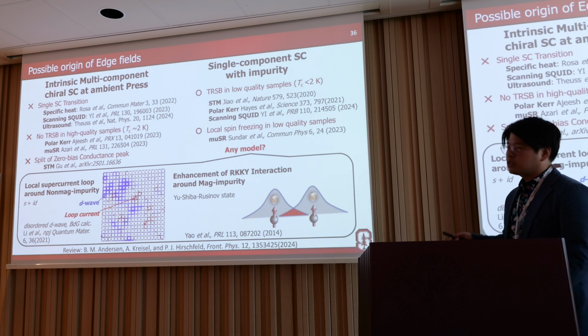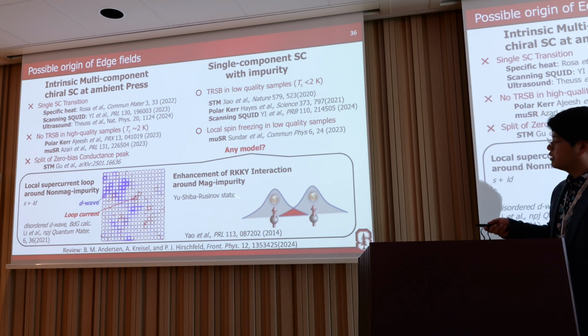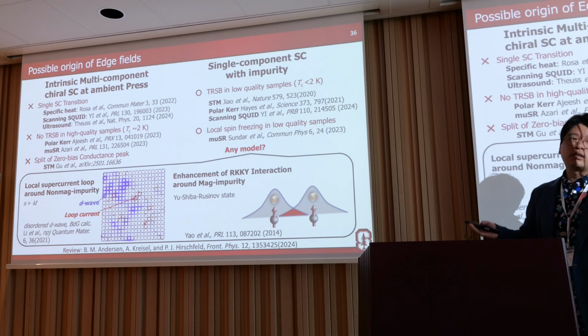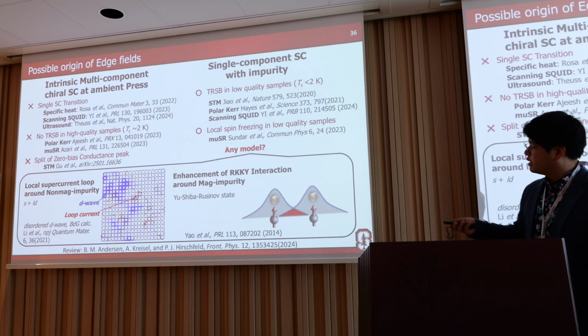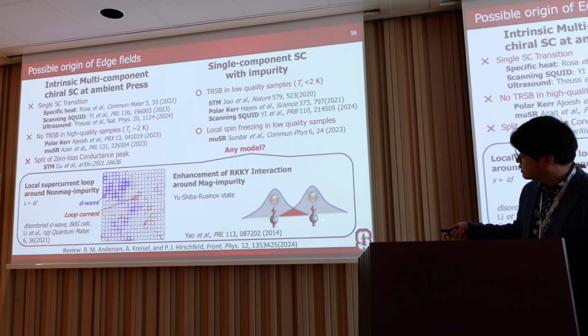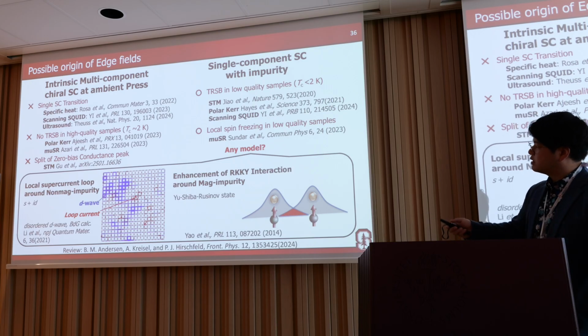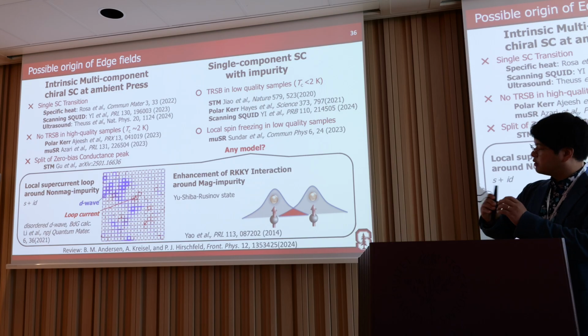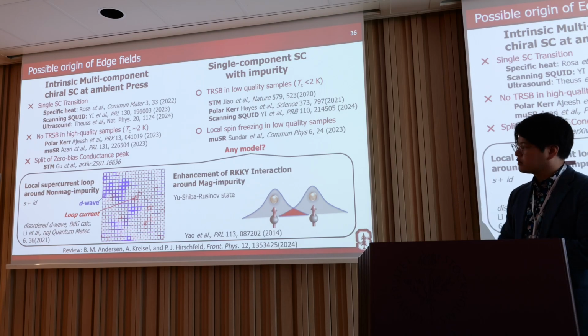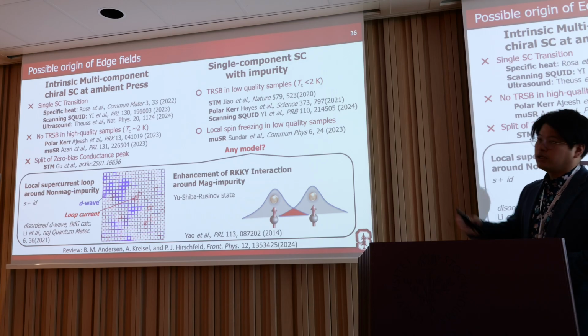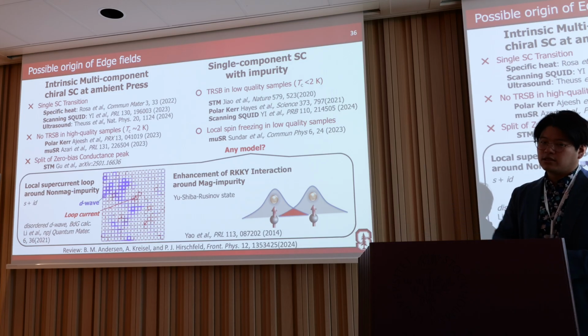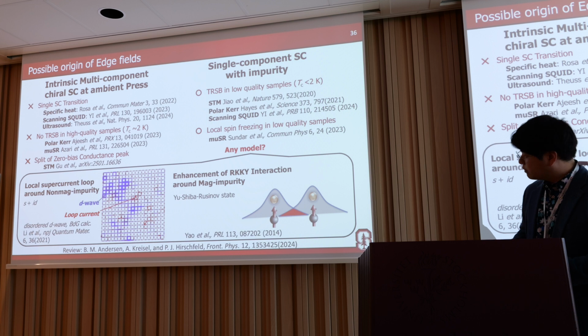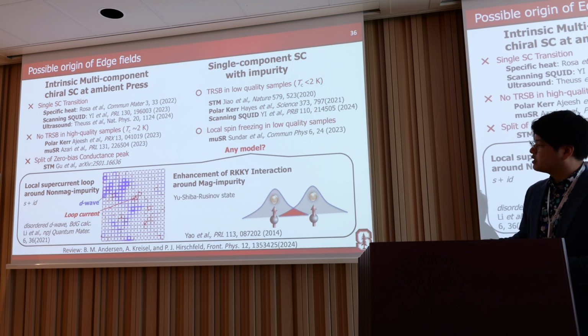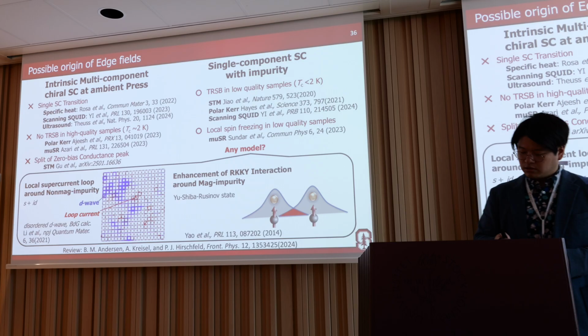The other one is the enhancement of the RKKY interaction around a magnetic impurity. So the state is a YSR state here. And this enhancement only happens in the superconducting state. If you change the distance, then the RKKY interaction goes from favoring ferromagnetic to antiferromagnetic. If the ferromagnet is stable only in the superconducting state, then we get the spontaneous magnetization. But we still don't have any microscopic model for UTe2.